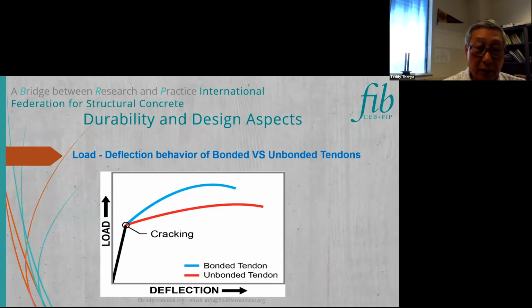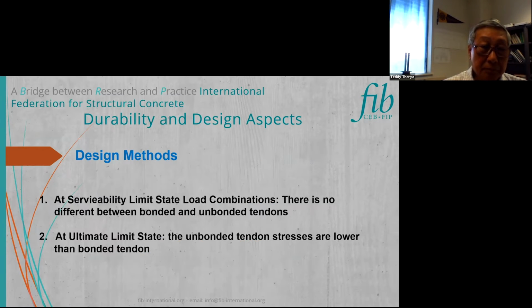This picture shows you the load versus deflection. If you can see from this diagram, from zero load to the cracking load, the behavior of bonded tendon and unbonded tendon is exactly the same. There's no difference. Beyond the cracking load, the behavior is quite different. Bonded tendon can achieve higher ultimate strength than the unbonded tendon. For the design method at the serviceability limit state load combination, there's no difference between bonded and unbonded when you do the design. At the ultimate limit state, the unbonded tendon stresses are typically lower than the bonded tendon.